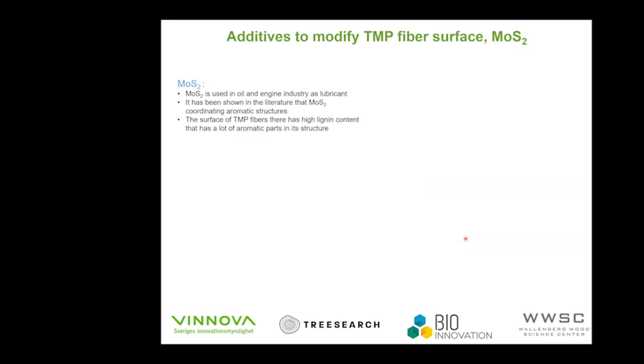And then the additives. I've talked about molybdenum disulfide, but it is interesting: molybdenum disulfide is inorganic and we are using it for a forestry product, but why? Molybdenum disulfide is already used in the oil and engine industry as a lubricant. It has been shown in the literature that molybdenum disulfide coordinates with aromatic structures, and guess what? In TMP, we have high lignin content, and lignin has a lot of aromatic parts in its structure. So we said, why not? It's a good idea, perhaps.